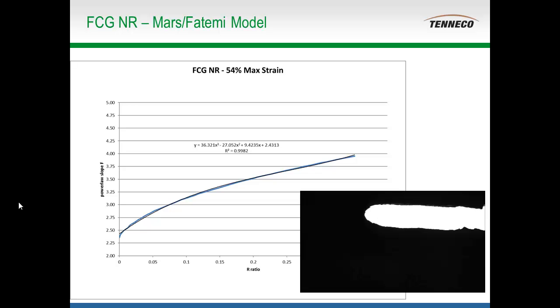So because it makes a much better movie, I've shown the maximum strain test that we did on this material. So at a 54% max strain, it starts off growing quite rapidly, and you'll notice that the crack stops growing towards the end of this movie, and that is represented as the R ratio increases. My correlation of the Mars-Fatemi model that's input into FE-safe rubber.